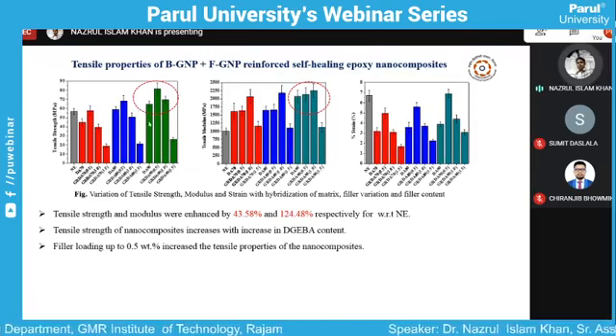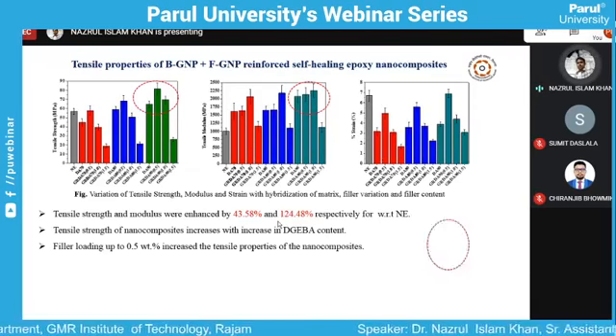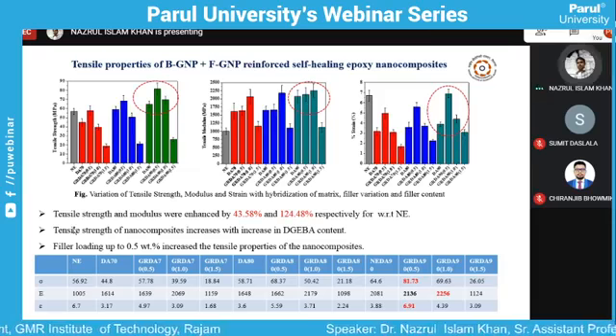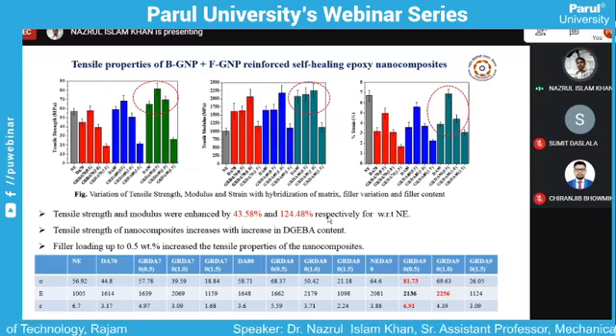We have seen that yes, it was able to improve the tensile strength also. You can see the tensile strength was improved by 43.58%, and modulus was improved by 124.48%, a two-fold increase was observed.